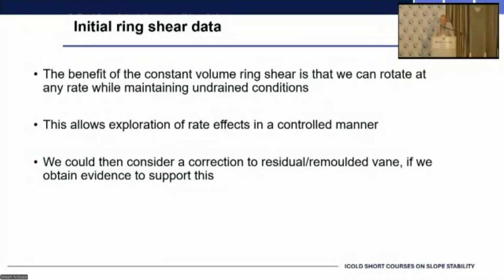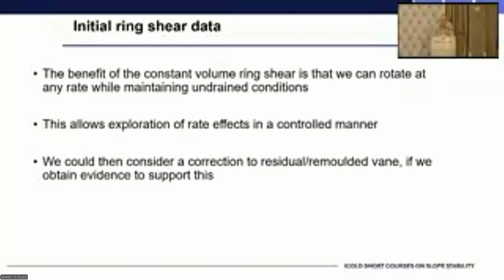I've mentioned this constant volume ring shear device. So it's similar to the ring shear I talked about yesterday. The trouble with a conventional sort of Bromhead type ring shear device is that as you're shearing the material, it can either dilate or contract in response to the shearing. So you're getting a change in volume. The constant volume ring shear device keeps the volume, as you would expect, constant by keeping the height constant. It's a tricky device to use, but then we can start looking at rate effects in a more controlled manner. And perhaps by comparing this device with many other kinds of devices, vane, etc., we can start choosing these large strain strengths more rationally in the future.